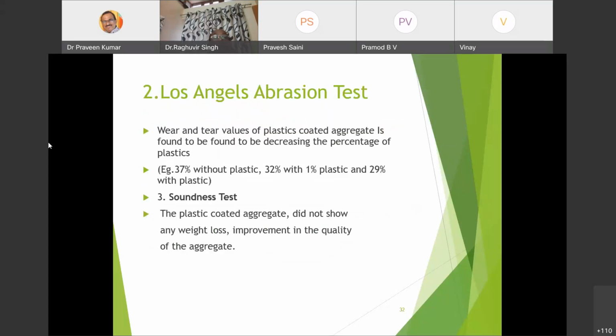The Los Angeles abrasion test value: the wear and tear values of plastic coated aggregate are found to be decreasing as the percentage of plastic increases. This is 37% without plastic, 32% with 1% plastic, and 29% with more plastic. The soundness test was also performed. The plastic coated aggregate did not show any weight loss improvement in the quality of the aggregate.